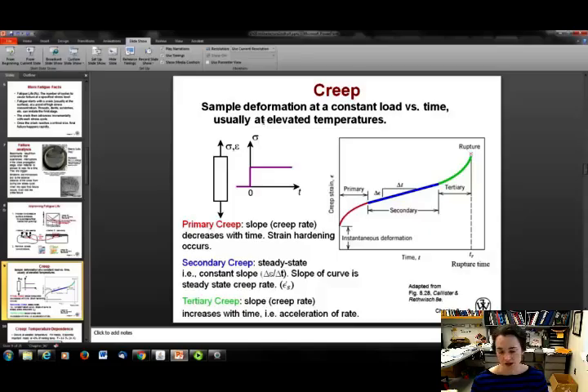Oftentimes these parts, say for example if it's in a jet engine or something like that, this also happens at elevated temperatures. The part gets really hot in service. So if you have kind of a constant load over time at an elevated temperature, your part is subjected to creep. Okay, so there's 3 stages of creep. First of all, when you first place the part in service, the very first day or whatever, first few days, this is called primary creep. And in that, you have, first of all, an instantaneous deformation. The part will deform the instant that you put it in service by some amount. It'll get all stretched out.